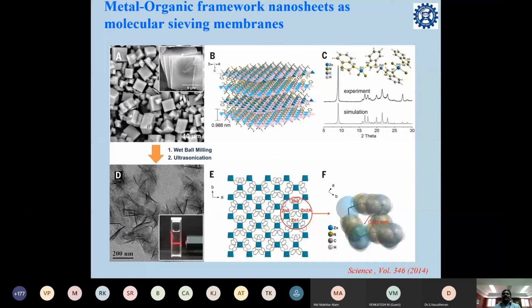And this metal organic framework usually occurs as a three-dimensional network structure. So that means it is very systematically arranged, and it has definite pores in between the organic frameworks. So these pores can act as molecular sieving membranes. That means through these pores the molecules can penetrate through. We can see here one example, zinc porphyrin. So this is zinc attached to porphyrin, and here we can see the pores at the right hand side, with a pore size of 0.21 nanometer. These pores can allow the small organic molecules, and it can act as molecular sieving membranes.